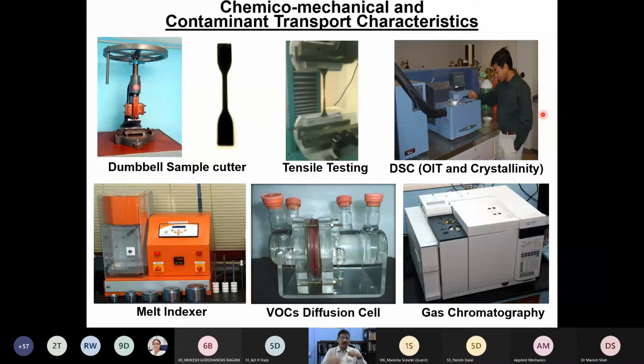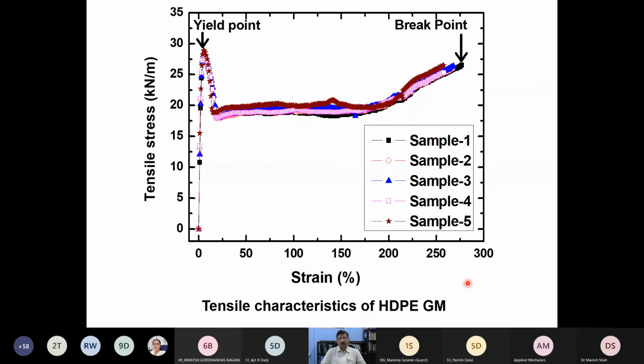So in order to measure the molecular weight, we employ an indirect method called the melt indexer, or melt flow index. We can really measure the polymer molecular weight this way. Not only the mechanical and chemical properties, we also measure these polymers once they are exposed to a certain level of radiation. We measure the diffusion coefficient by using this kind of cell, which is used for volatile organic compounds, with a GC, gas chromatograph. So this is the way you assess the photodegradation of a given polymer.